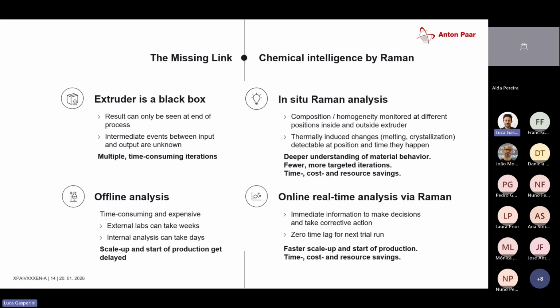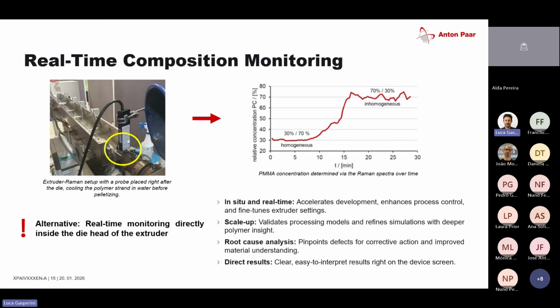So yeah, online real-time measurement. Now I brought some examples. Here, for example, we had a PC PMMA measurement. We were adding PC to PMMA, and as you can see here, we were observing the composition. Down here, we had 30% PC and 70% PMMA, and then over time we just increased the amount of PC. What's interesting is that here it's pretty homogeneous, so the mixture was working very well.